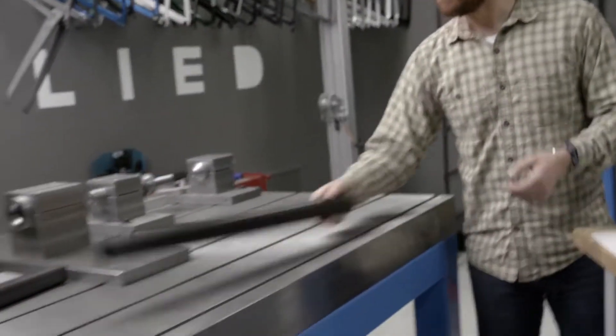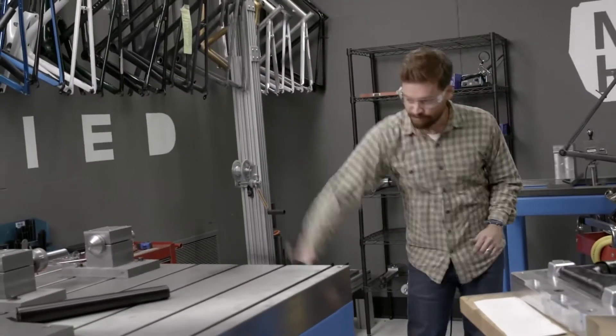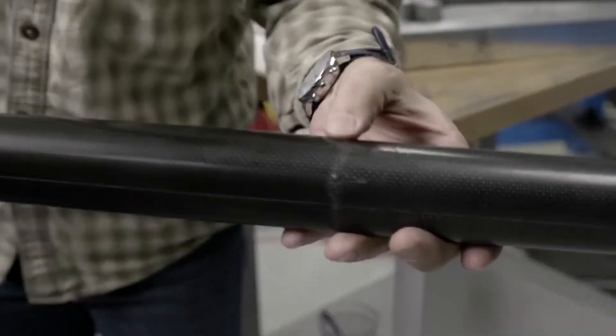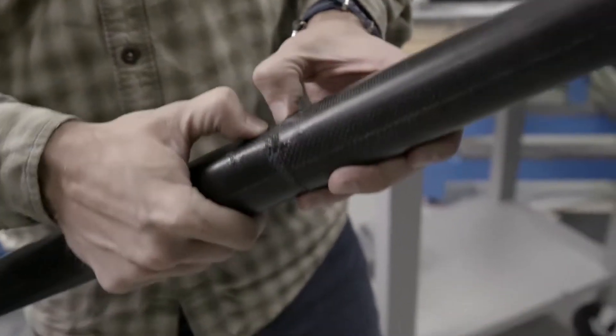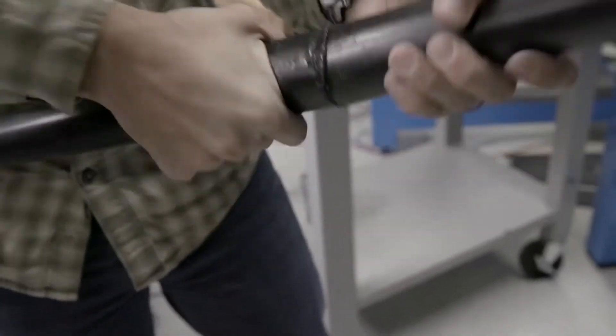Now we'll do something very similar to the Innegra tube. You can see that the Innegra tube is still very much intact. The under layers are broken, but that Innegra is holding everything together. We could probably impact this thing a few more times and it's still kind of holding together. That's one of the key reasons we use Innegra in our bikes — to help prevent catastrophic failure.